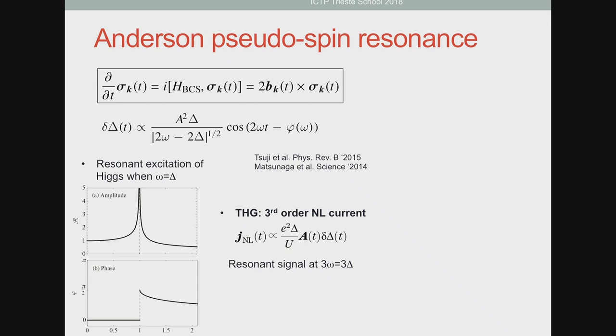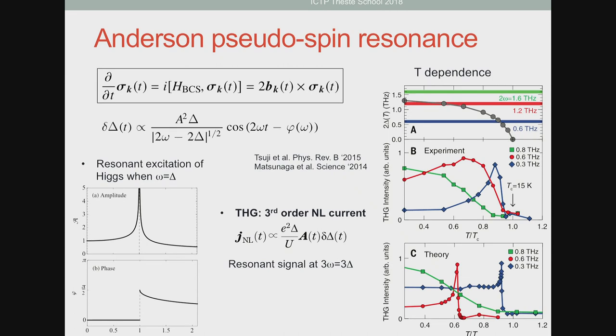So in fact, if you think about it, it's exactly like a Raman process, right? You shine light at delta, you collect light at 3 delta. So if I were a Raman guy, I would say, OK, so I'm now going to plot everything in terms of Raman shift. So 3 delta minus delta, 2 delta, oh, it's my 2 delta peak. OK, but then you are going to say to me, wait, could this be the pair breaking peak there? I will come back to that in a moment. So anyway, you expect a resonance signal when you are exactly matching the omega equal delta condition.